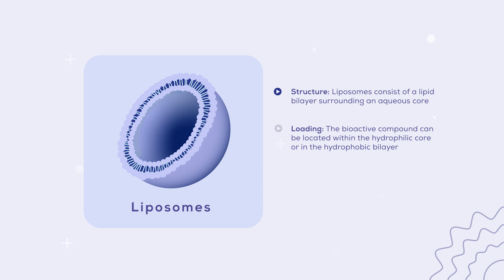Bioactive compounds may be contained either within the hydrophilic core or in the hydrophobic bilayer, and this positioning depends on the properties of the bioactive compound itself. Formulations can include the use of synthetic and naturally occurring phospholipids, as well as surfactants. Liposomes can come in many sizes, but typically fall between 70 to 2,500 nm.